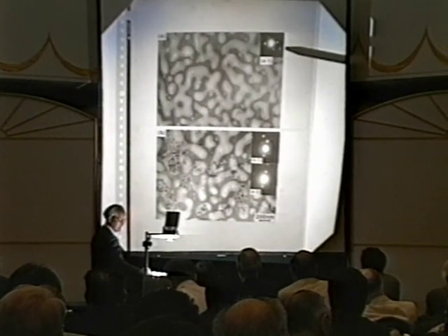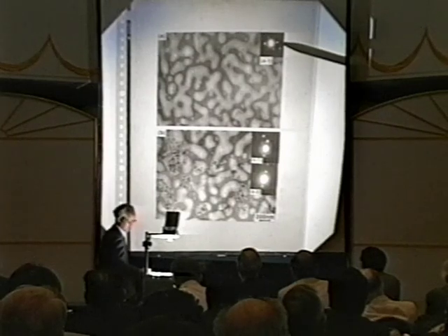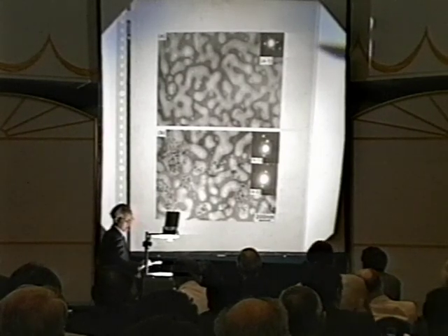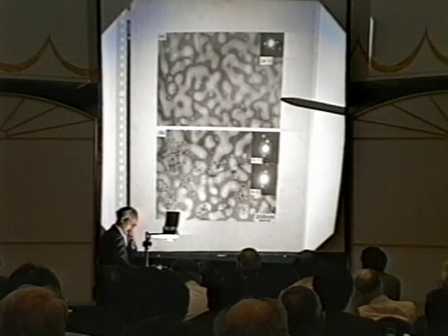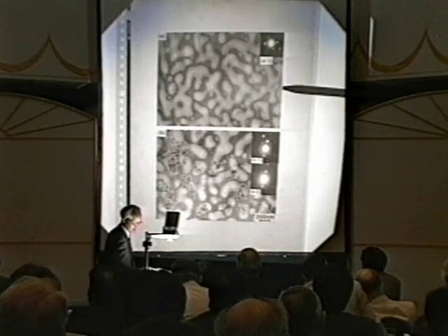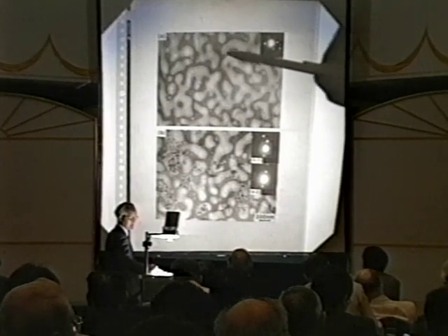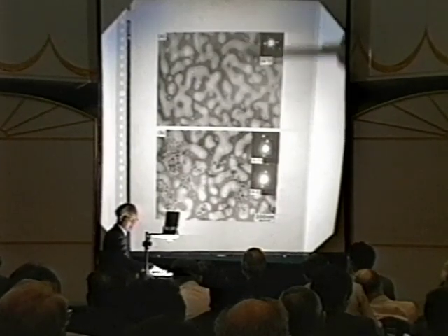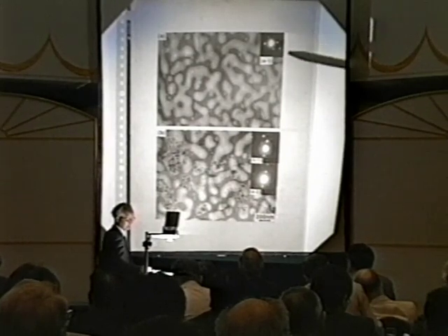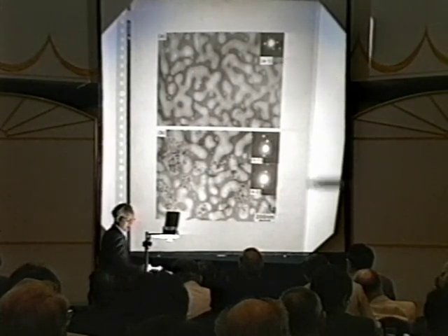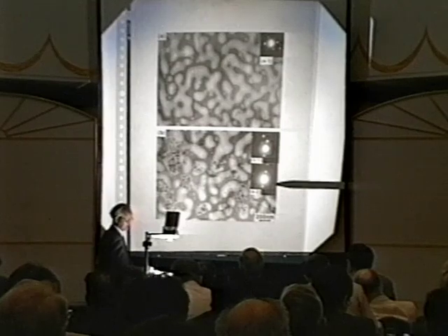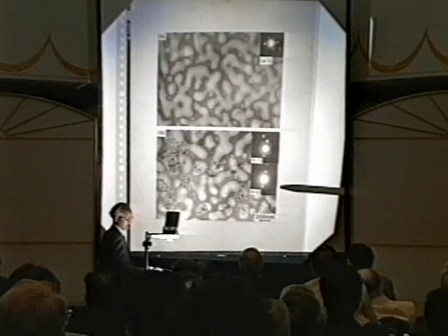This electron diffraction spot shows that in case of hydrogen implantation, everywhere in the specimen is single crystalline. And it's also single crystalline in the deuterium implanted case.